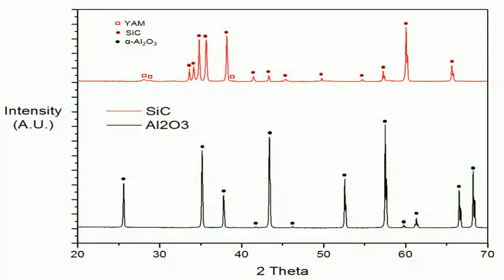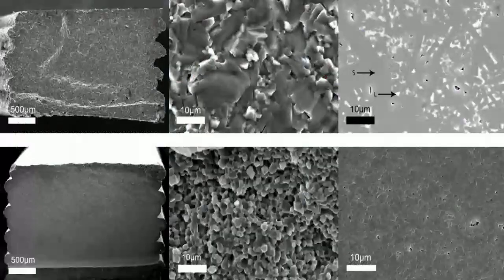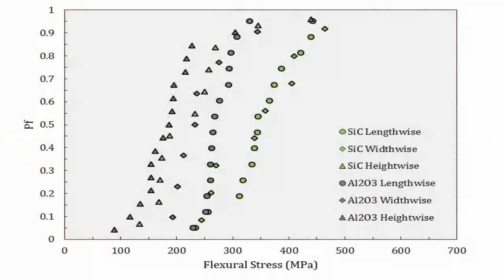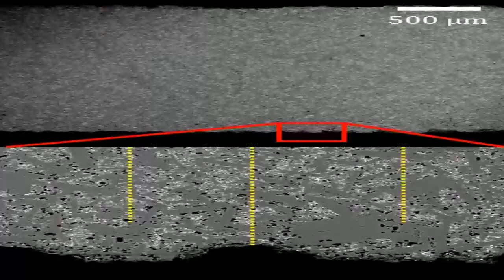That's important to know. How did robocasting arrange these flawed platelets? You mentioned alignment. Right, those shear forces during extrusion through the nozzle did indeed align the platelets along the direction of flow, just as expected. And this created a very specific microstructure within each printed filament. They called it a core shell structure. Core shell? Yeah, in the outer shell of the filament, the platelets were highly aligned, sort of like concentric rings following the filament shape, but in the very center, the core, the orientation was more random.